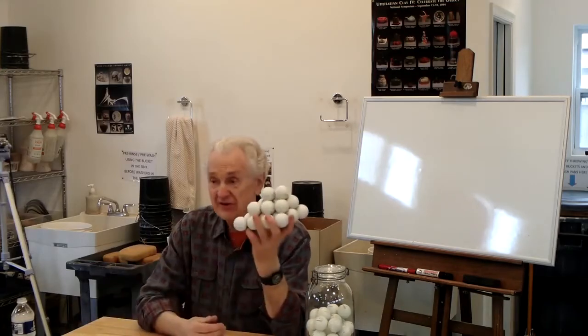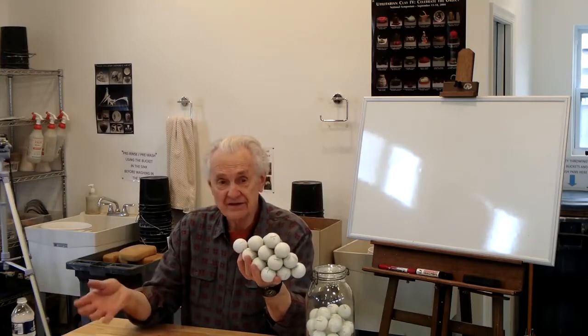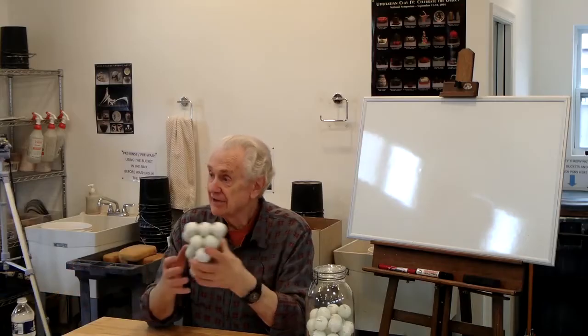And the reason why that's important is it really affects the properties. One of the properties, for example, is that most materials that are crystalline, or crystals like this, have a definite melting point. When you heat them up, you get to a certain point, they melt, like ice is a good example. Okay? But a lot of glasses don't. They don't melt at one specific point. As you heat them up, they get softer and softer, and finally they get runny, and finally they turn to liquid. So that's just one of the properties, and that's due to the way the atoms are arranged. So glasses have very unique properties compared to crystalline materials. And that's fortunate for us, because if they were crystalline, we wouldn't be able to use them as glazes.